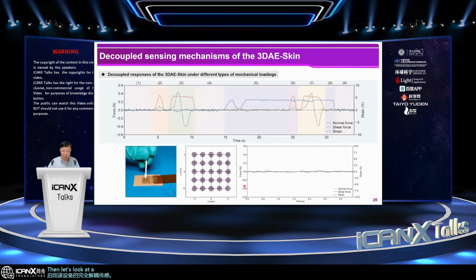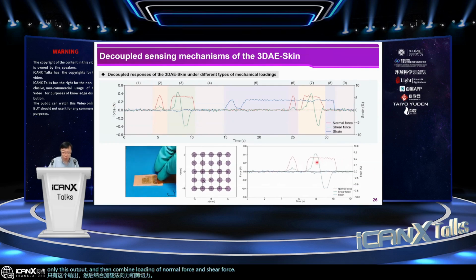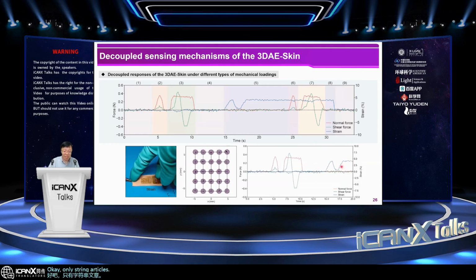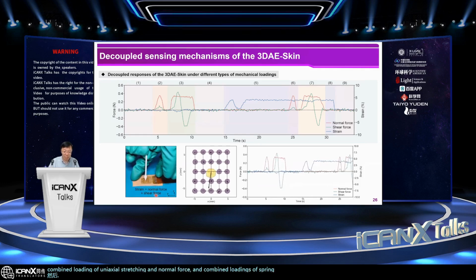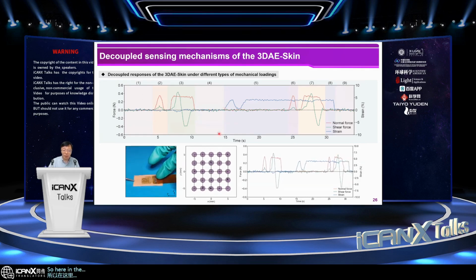Then let's look at a testing result. This one shows a sequential process. Initially, we only apply a pressure loading to the central unit, only this output, and then combined loading of normal force and shear force, two outputs. Then we apply a pure uniaxial stretching, only strain outputs. And then combined loading of uniaxial stretching and normal force, and combined loadings of strain, normal force, and shear force. Here in the top figure, the red curve denotes the normal force responses, the green curve is the shear force response, and the blue curve is the strain response. So these experiments show clearly the decoupled sensing capability of the 3DAE-Skin.